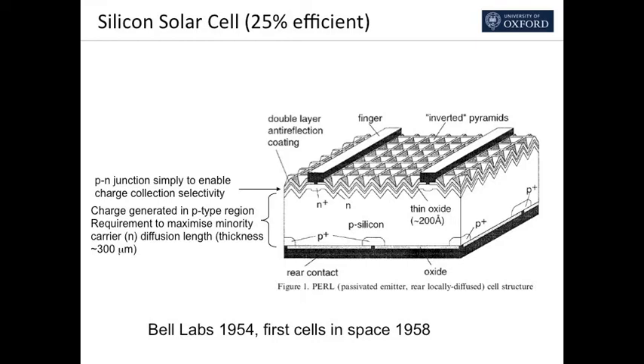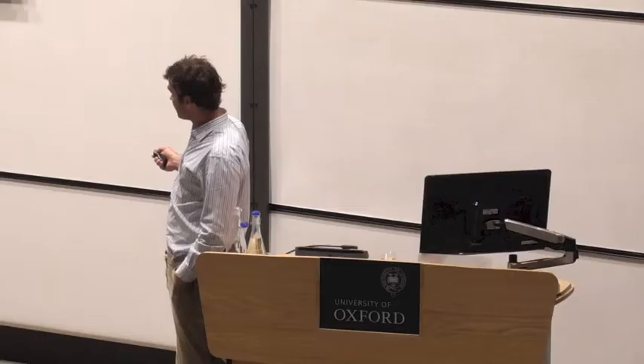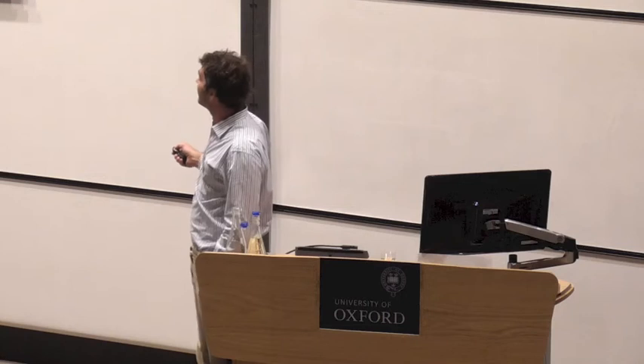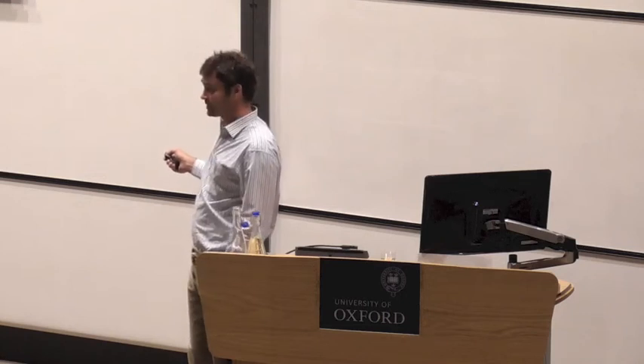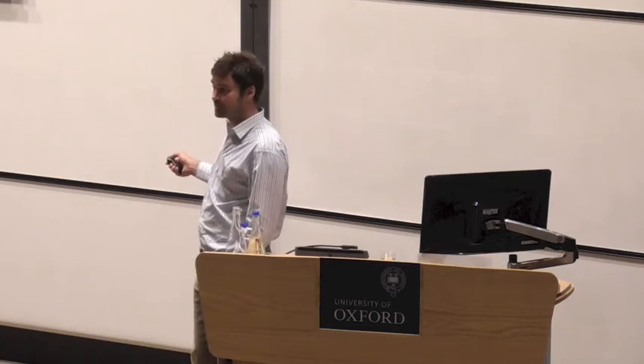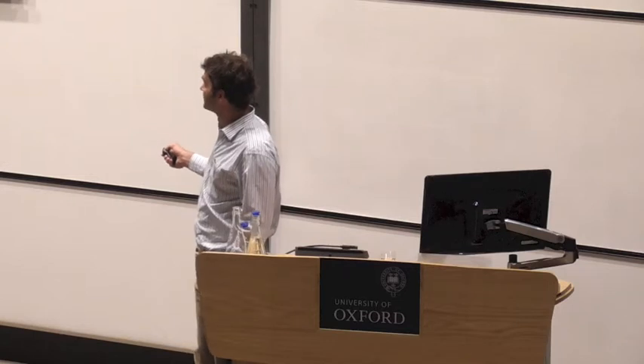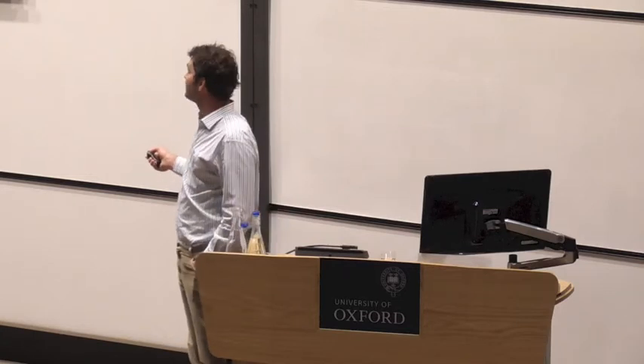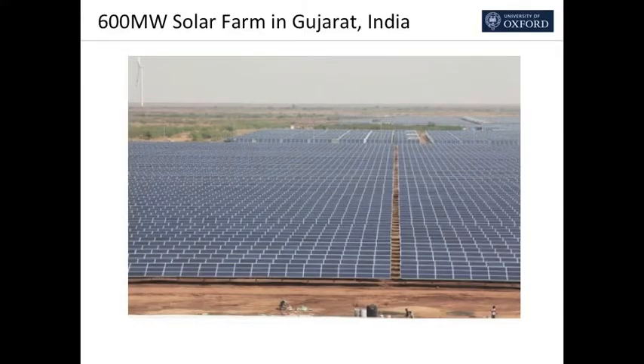But silicon only works when it's very, very pure. If there's any defects in there or any impurities, the charge doesn't get out. So the reason why silicon PV has been historically expensive is that it's been a very energy-intensive, cumbersome process of making these really pure materials and then putting on all these contact layers very carefully and stopping any defects or impurities at the interfaces. Despite that, it's done pretty well and is doing pretty well.